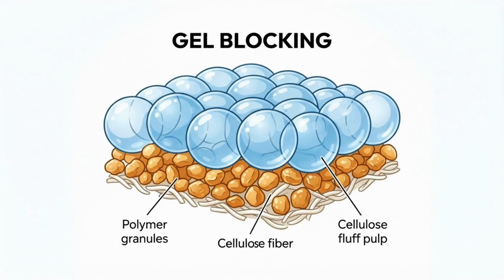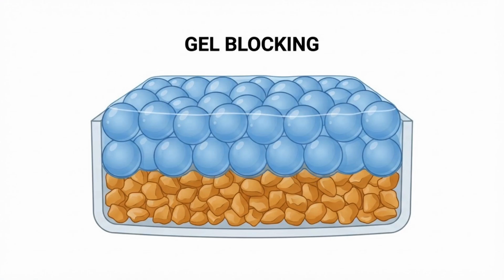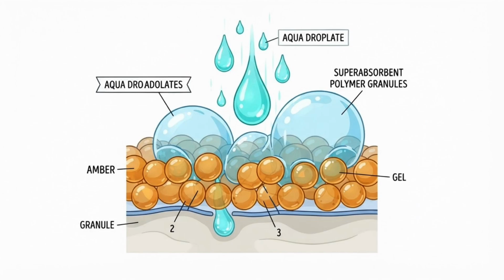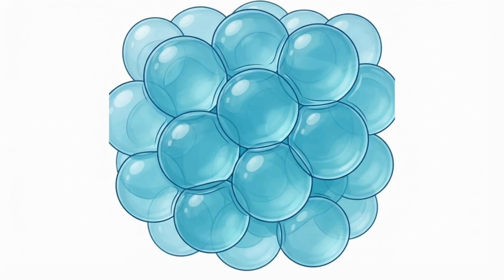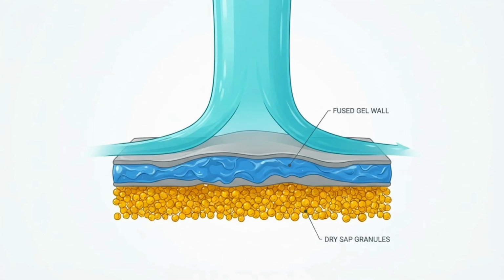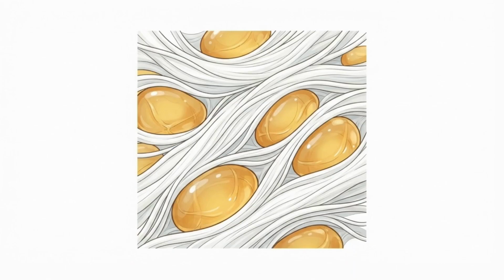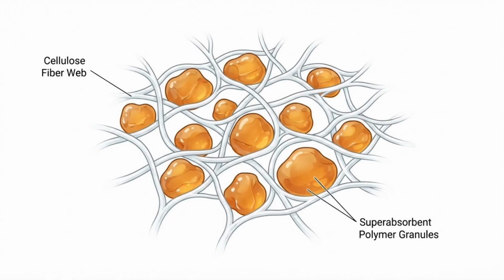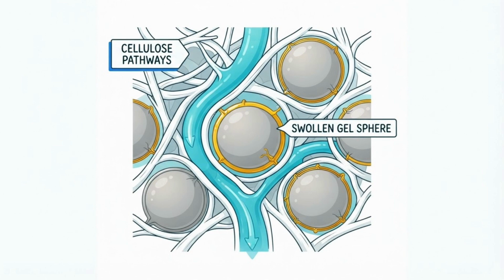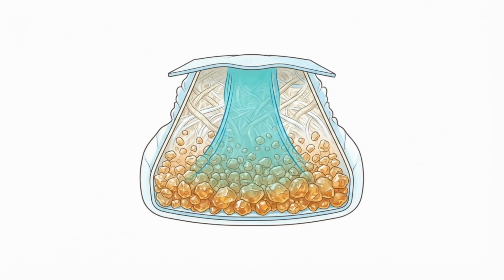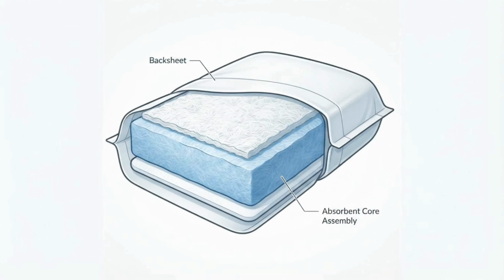The ratio of fluff pulp to polymer is meticulously calibrated. If there is too much polymer and not enough fluff pulp, a phenomenon known as gel blocking occurs. The outermost granules of polymer would absorb liquid so quickly that they would swell into an impenetrable wall of gel, blocking the remaining liquid from reaching the dry polymer underneath. The cellulose fibers act as microscopic highways, keeping the polymer granules separated and ensuring that liquid bypasses the swollen outer layer to reach the dry material deep within the core.